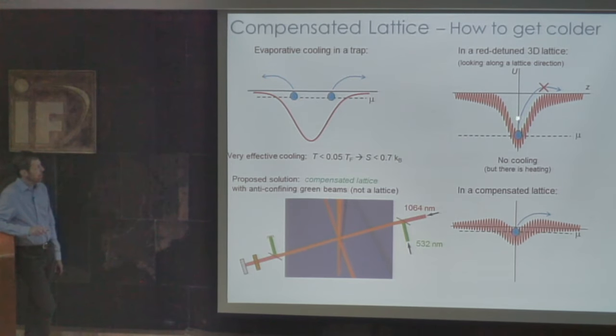So this is produced by the infrared beams, and I'm superimposing on top of that this blue detuned laser beam, and that gives me a knob, an adjustable parameter, where I can adjust the chemical potential to be anything I want, and I can encourage evaporation. This beam is not retroreflected upon itself. This is a beam dump. So this is not a lattice, but it's modifying the confining envelope of the existing lattice.